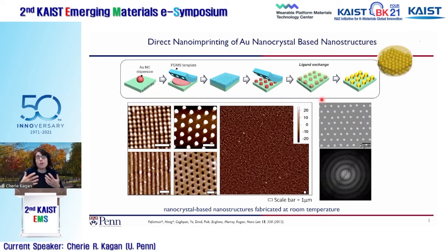I'll also share with you the idea that one of the advantages of nanocrystalline materials is, of course, that they can be dispersed in solvents, they can be handled like inks, and we can think about different ways to pattern these materials and integrate them in devices. When we first started working on this, my postdocs, Aaron Farfman and Sung Kun Hong, had been working on this. And Sung Kun really came up with this process where we could use imprint lithography and imprint directly into a dispersion of the nanocrystals and create patterned structures on the surface. Then you could simply dip it in, do the ligand exchange, and convert each of those patterned features into the metal.